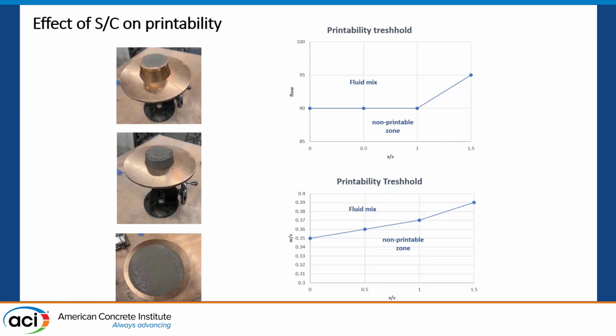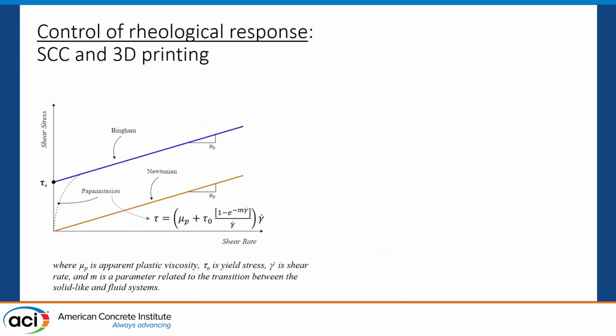And finally, we come to the point that we still need to characterize the material, and we need to use rheological models. What we have as a classical model is Newtonian response or Bingham response, and obviously with 3D printing, we like to see yield in the system. So a Newtonian system cannot be used for 3D printing, because you need material to sustain the stress. And in reality, the Bingham model is represented for many systems by the Papanastasiou model. So you have a curvature associated with the curve.